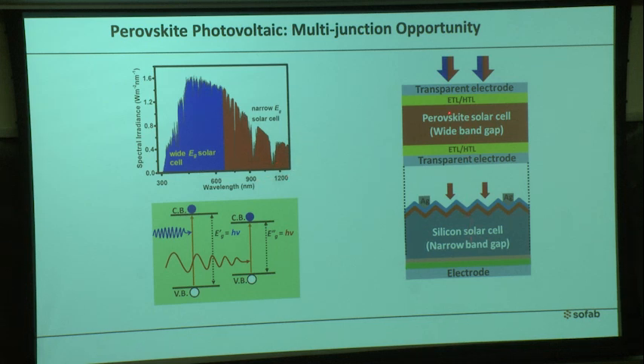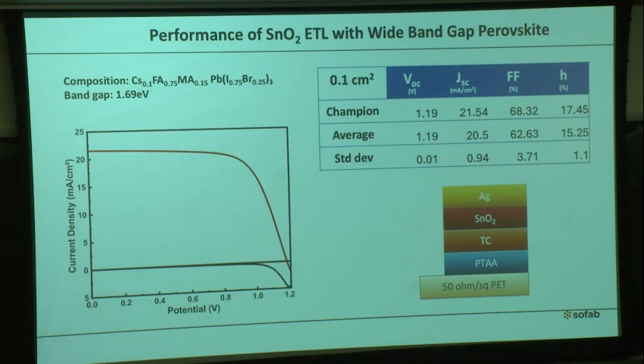If we stack a perovskite solar cell on top of the silicon solar cell, we can do better light management, and then we can utilize a wide range of radiation, and get higher power conversion efficiency. That's why, to make a multi-junction device with silicon solar cell, we need a wider bandgap perovskite. And how does the tin oxide, that new material we fabricated, work with a wider bandgap perovskite? After that, to make silicon-perovskite tandem devices, the first step is we need to design a wider bandgap perovskite. Here we designed a wider bandgap perovskite with this composition and bandgap up to 1.69 electron volts, which is suitable to make perovskite-silicon tandem devices.